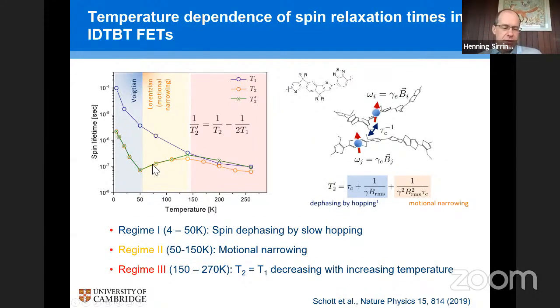But then around 50 Kelvin, you see this characteristic turnover where the spin relaxation time T2 starts to increase again. And that's a regime that some of you will be familiar with. It's a motional narrowing regime. As the charges move faster and faster, they start to average more effectively over the local magnetic field environments. And these fluctuations in the local fields are less able to dephase the spin. And so you have a regime where spin relaxation becomes less and less effective as the charges move faster and faster.